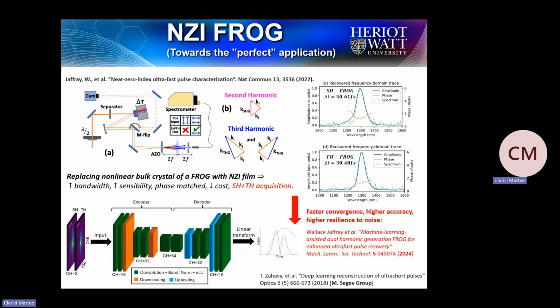Another application, because again, what we have here is a very nonlinear material. So fundamentally, wherever you are using nonlinearity, you can think of replacing your standard nonlinear material or crystal with this kind of compound. This one is another example. This is a frequency resolved optical gating system, so it's a FROG. It's a system designed to measure the amplitude and phase of ultrafast pulses. Without going into the details, fundamentally, it works by having the pulse that you want to measure have a nonlinear interaction with a replica of itself in a nonlinear crystal, and then you record the nonlinear interaction, which can be a second or third order or a third harmonic signal, as a function of the time delay between the two. And from this FROG trace, you can, through a very established algorithm, retrieve the information that you want.